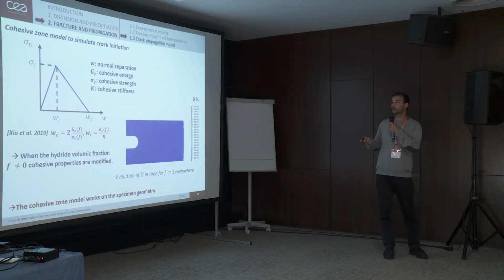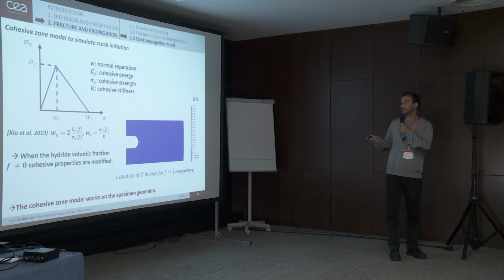And finally, to model the crack propagation and the crack initiation, we use a cohesive zone model. This model consists of an additional mesh on the ligament, and it's driven in normal separation. So once the normal separation is bigger than the critical normal separation, there is decohesion and fracture and crack propagation. So this critical normal separation is a function of the hydride volumic fraction. So once the hydride volumic fraction is different from 0, the cohesive zone properties are modified. And you can see here a test on the specimen geometry with f equal to 1 everywhere, so it's only hydride. And you can see that the cohesive model works on the specimen geometry because the crack propagates.